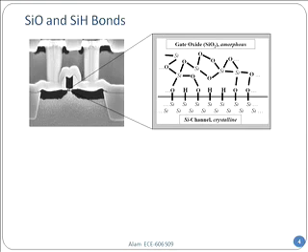The other type of bond that could be broken is silicon-oxygen bonds, and that's the second bond that can also be broken. Now you will notice that in this list I didn't put silicon bond breaking. Why not? There are lots of silicon bonds in the crystalline phase. Because crystalline materials are deposited at very high temperature. Their bonding is very strong, and they are in the crystalline phase. Everybody is where they are supposed to be, and therefore it is not easy to break at room temperature, as you are just operating the transistor, right? In your computer, you are just using it at room temperature.